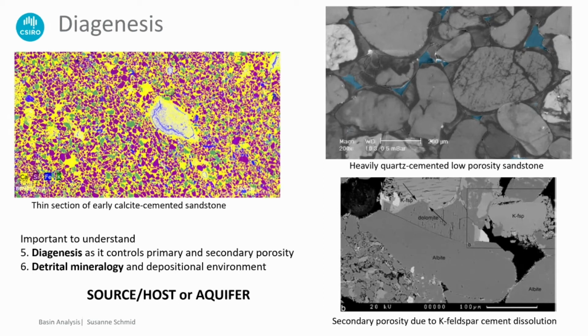So you see, if you haven't had any mineralization up to that point, and that usually starts around 90 degrees, quartz cementation then continues going on until about 150 burial depth. So you're blocking all your pores. You will not have any connectivity. So there's no way of getting any later fluids through that system. It's not going to be your aquifer. So just keep that in mind if you see a sandstone. Really make sure you understand the diagenetic history.